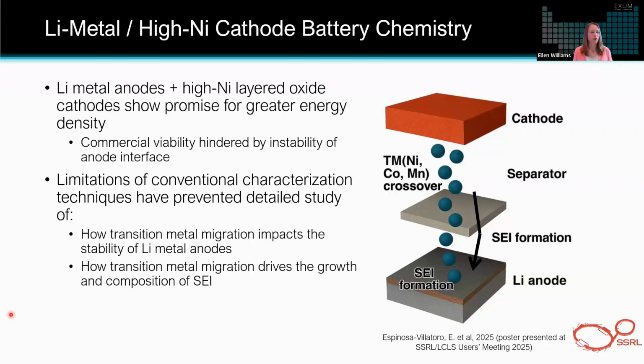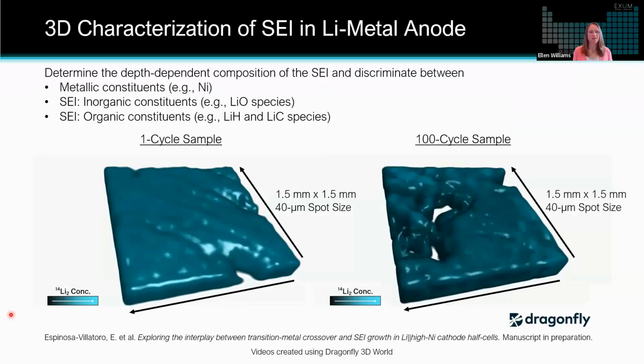And as we've mentioned, there are limitations with some of these conventional characterization techniques to fully understand the stability of the lithium metal anode and how these transition metal migration might be impacting the SEI layer, solid electrolyte interface layer. So what you're looking at on this slide is just a preview of a manuscript that is in preparation right now. You can see the title on the bottom of the slide here. And so I encourage you to keep an eye out for when this manuscript is published, because there's a lot more information that's included in this manuscript, especially including how dopants have been explored in order to mitigate some of this transition metal migration.